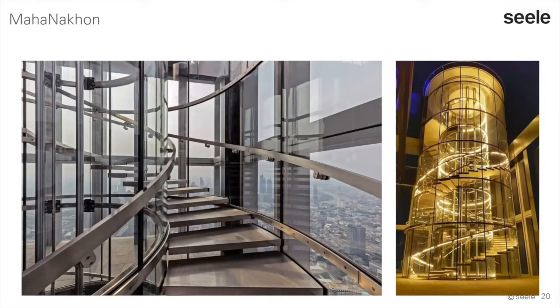So now this glass cylinder is not fixed to the construction you see right besides the glass cylinder or behind the glass cylinder there. The glass cylinder is standing completely free. How to achieve that this cylinder can stand completely free without any steel construction or whatsoever? What we did here, we were introducing in each of the vertical glass joints of the outer cylinder tension elements. And these tension elements, they are pulling down the roof. And by pulling down the roof, they are stabilizing the whole construction. So this is a very modern approach, I would say, to build in itself stabilizing glass cylindrical staircase without being fixed and stabilized by any adjacent construction around it.